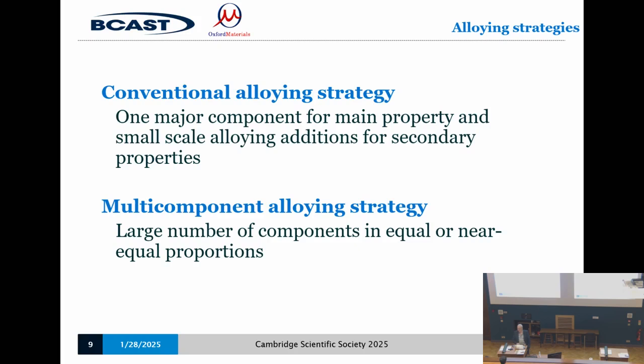Nickel superalloys are nickel because nickel's got a higher melting point, so that solves the main problem. But then you add a little bit of titanium or aluminium to make it a bit stronger, and you add a little bit of chromium to make it corrosion resistant, and both of those are important. So that's a very typical example.